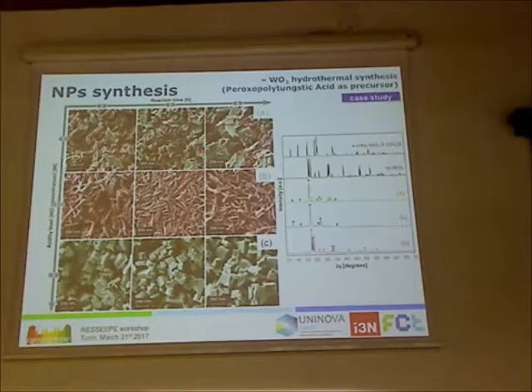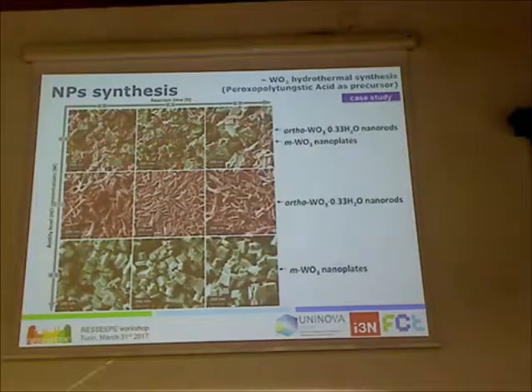So this is what we do in the lab, and we end up with tungsten oxide, so it's the case study here. Tungsten oxide is the most used material for electrochromic windows, with the orthorhombic crystalline phase. That happens also to retain some water, coordinated water inside. This is very important, I will explain later.